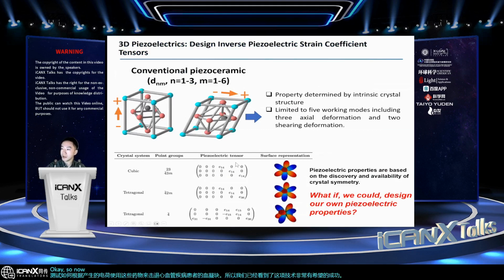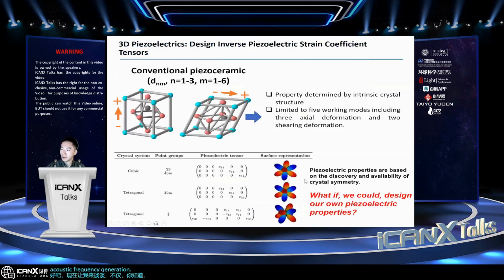Okay, so now let me talk about not only acoustic frequency generation, but also low frequency, which is the actuation mode. We also use them for robotic applications. Again, this comes from my earlier slides on piezoelectric crystals in nature. You can only have a few existing piezoelectric tensors, governed by the asymmetry of the natural crystal. So what if we could design our own piezoelectric properties? What we want is artificial crystal building blocks, for example a cubic block, but with your own tensor.